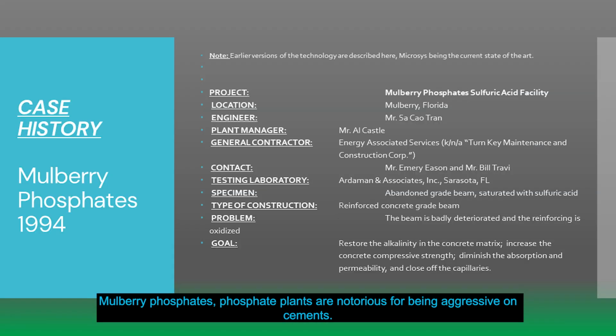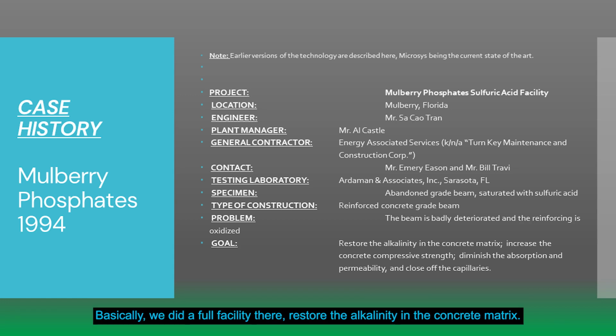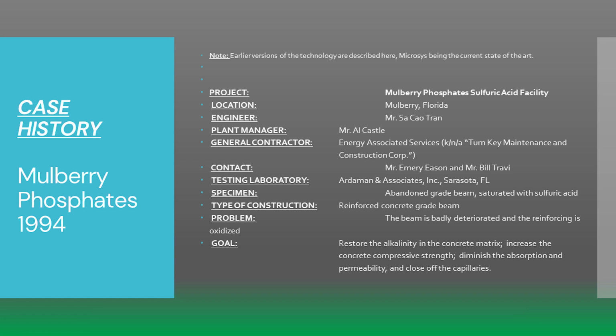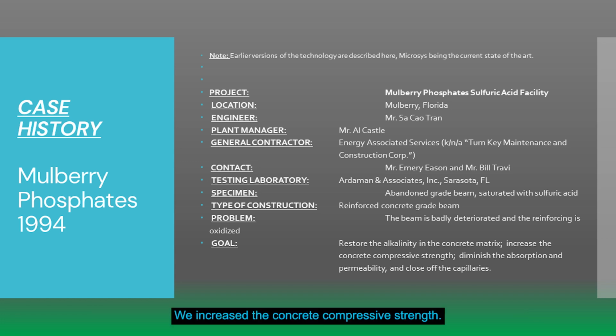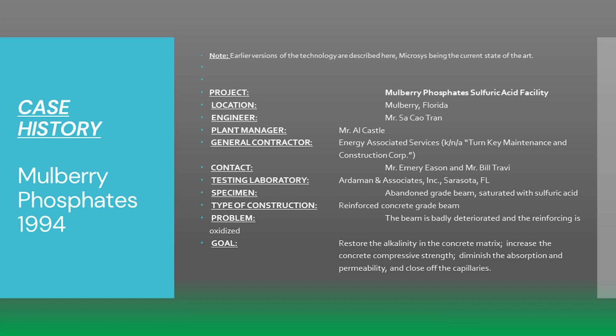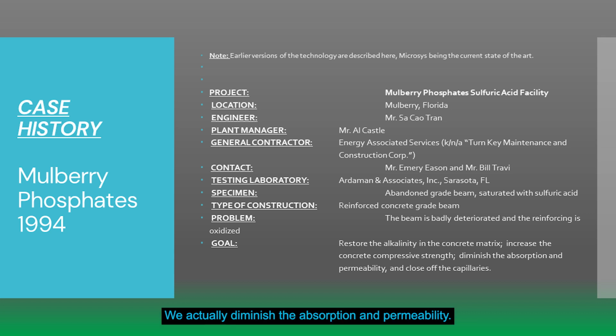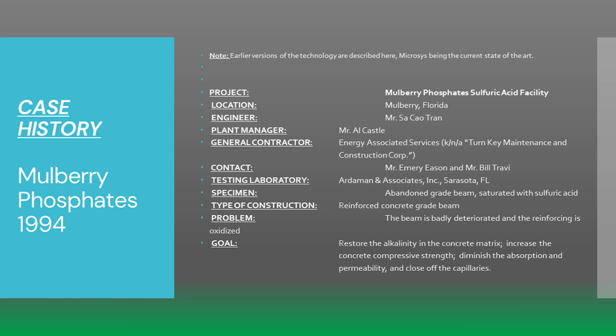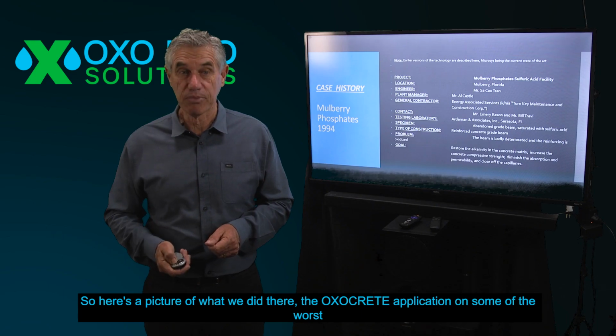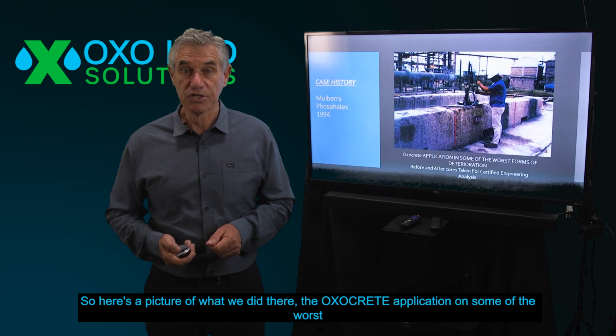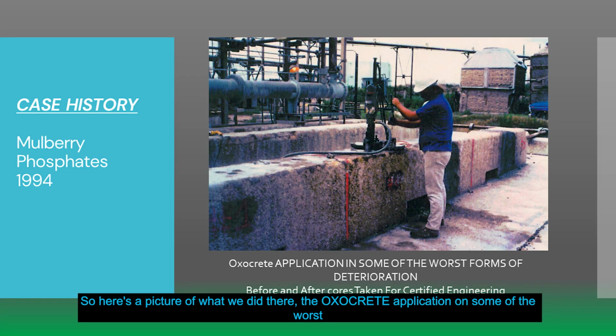Mulberry Phosphates. Phosphate plants are notorious for being aggressive on cements. We did a full facility there. We restored the alkalinity in the concrete matrix. We increased the concrete compressive strength. We diminished the absorption and permeability in there. We filled up all the capillaries and we stopped the problem. So here's a picture of what we did there.